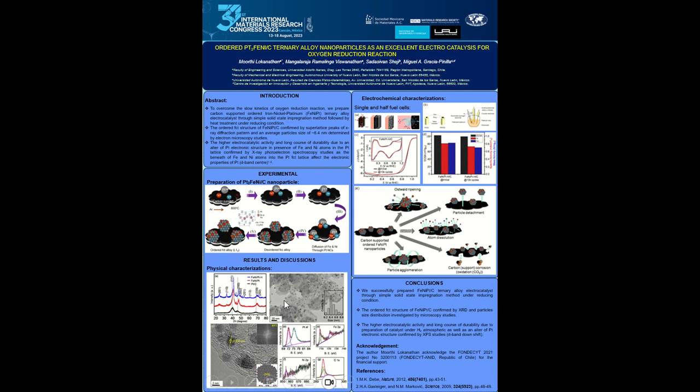Then we employed microscopic analysis. From the microscopic analysis, we found that the individual nanoparticles are deposited on the carbon support, with the majority of nanoparticles having a size of 6.4 nanometers.